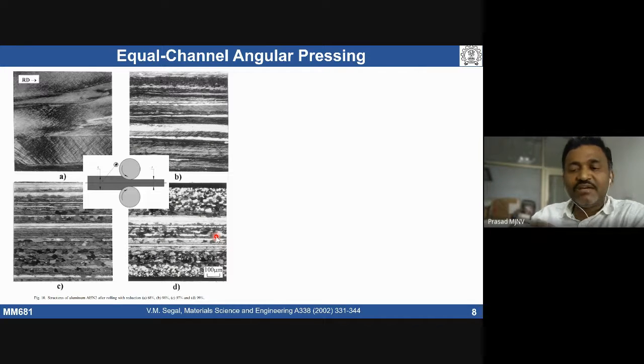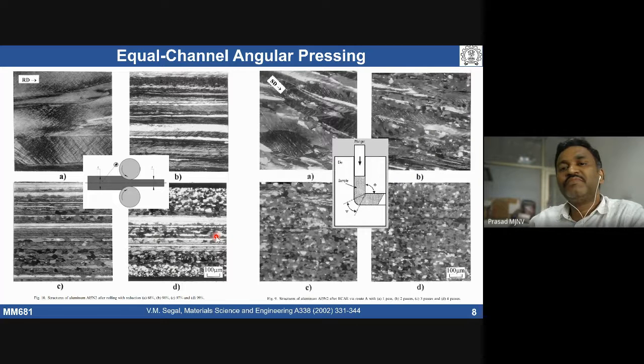If I use ECAP, there is a shearing activity happening. The grains are undergoing shearing in a single pass, then a second pass, third pass, fourth pass. What is the difference between these two? This one is rolling, the other one is ECAP. Look at the microstructure development. The elongated grain structure is almost not there; we are seeing an equiaxed microstructure as much as possible.